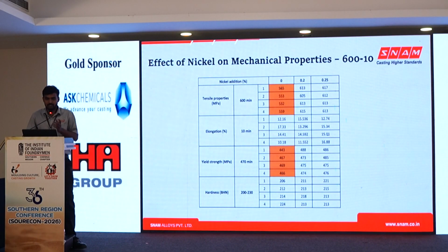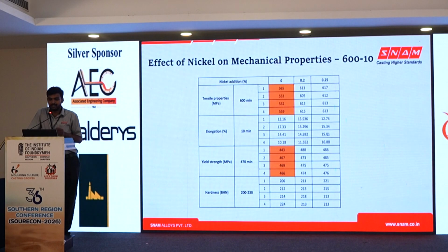If the silicon percentage goes more than 4.3, it may have a tendency to form chunky graphite or segregation of alloying elements in the microstructure. So we can't increase the silicon to increase mechanical properties like yield strength and tensile properties. So we have added nickel to increase the tensile strength without affecting the ferrite phase. We have added 0.2% and we have achieved almost all mechanical properties as per the standards for 600/10 grade.